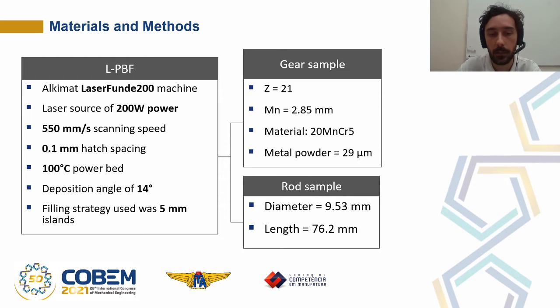The laser powder bed fusion process was performed in the Alkimat LaserFunde200 machine with 200 watts of power, 550 millimeters per second of scanning speed, 0.1 of hatch spacing, and a powder bed of 100 degrees Celsius, a deposition angle of 14 degrees, and the filling strategy was islands of 5 millimeters.